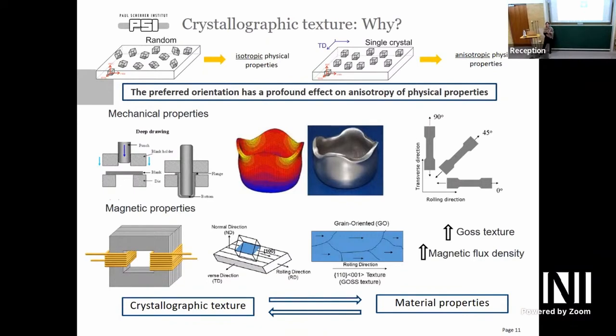No, but I will explain why. This is a general assumption. We are not just using neutrons, we can use EBSD, for example, and the scale there is completely different from neutron interaction. So basically, we are assuming that you need to have a distribution. How big or how small your crystal should be in order to have this distribution is something that is not fully clear. A lot of people use a really tiny EBSD analysis now to say the texture of my sample is this one. I fully disagree with that because that's not an average sample.